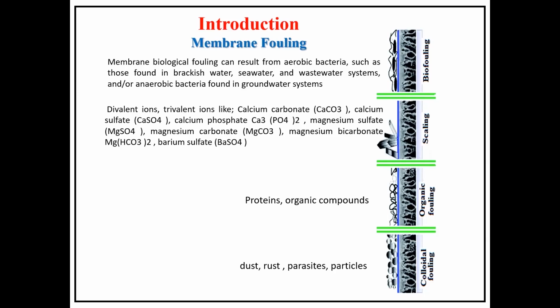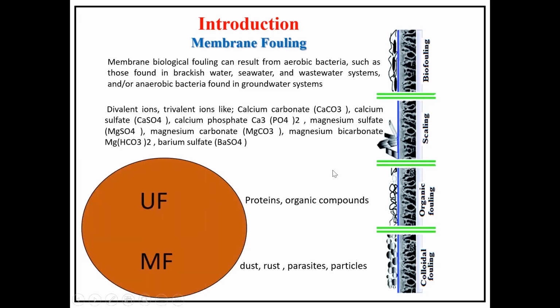The fourth one is biofouling, where biological fouling on the membrane can result from aerobic bacteria, which are found in brackish water, seawater, or wastewater, or anaerobic bacteria, which are found in groundwater. Actually, colloidal fouling and organic fouling are mostly found in microfiltration and ultrafiltration membranes, and these can be removed by backwash. Scaling fouling and biofilms or biofouling mostly occur in nanofiltration and reverse osmosis membranes, and these need chemicals to treat them.